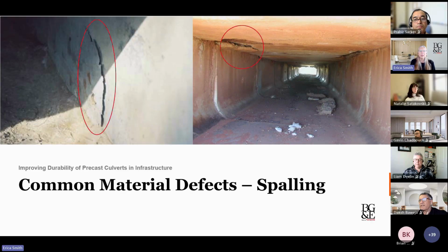Things like delamination, where you have a discontinuity in the surface of the concrete, just before you get the spall. You can usually tell that you've got delamination by whacking it with a hammer, and then you get a hollow sound behind.